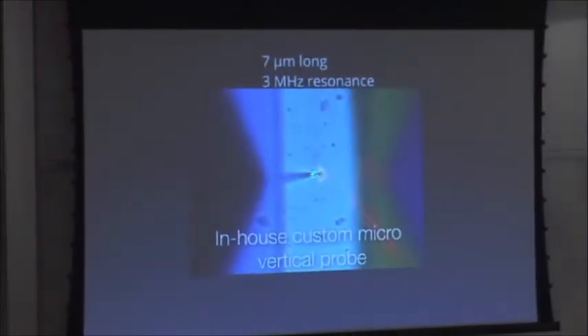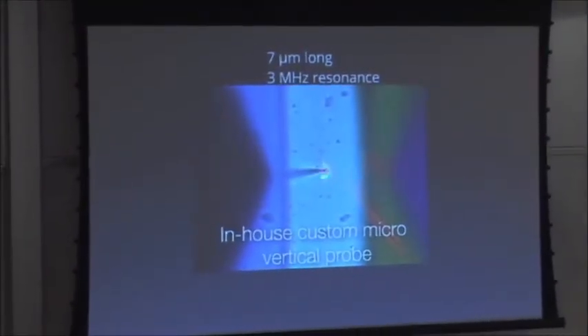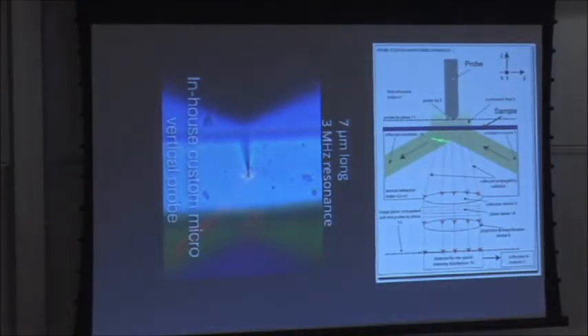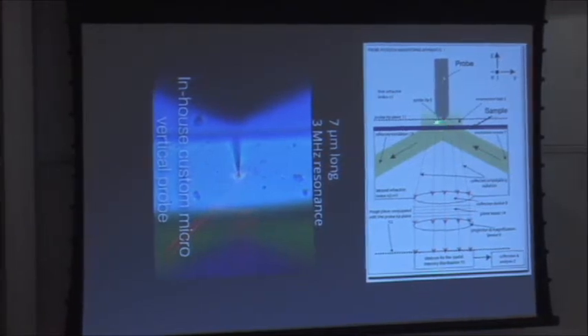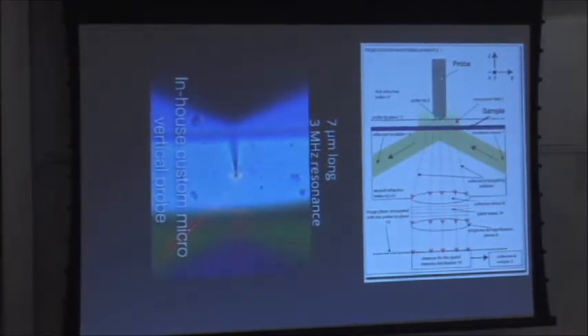So here's a probe. Here's a 7 micron long probe, 3 megahertz in our microscope. You can just about see the end shining. The end is shining because it's sitting in an evanescent field. So we create an evanescent field on the surface, we dip the probe in, and the probe diffracts and scatters. We collect the scattered light, and by looking at the position of the scattered light on the detector, we can measure the position of the probe to about an angstrom.